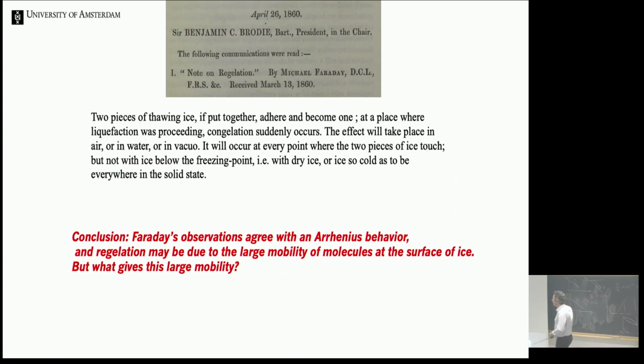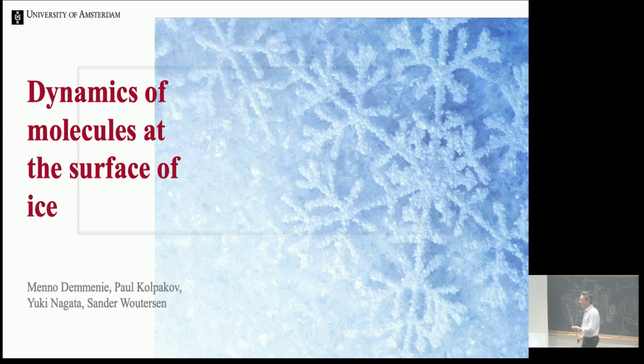Let's go on. So I will answer your question. But not before coming back to Faraday, because what Faraday said is, I can put those two ice cubes together, and this will work at relatively high temperatures, but it will no longer work at low temperatures. And I think that is in perfect agreement with the fact that this is an Arrhenius process, where the rates decrease exponentially with decreasing temperature. You would simply need a lot of time for two ice cubes to sinter at very low temperatures. So I think this also explains the observations of Faraday. But the million-dollar question is, of course, what is the dynamics of the molecules at the surface of ice? That's the question that we really want to answer.